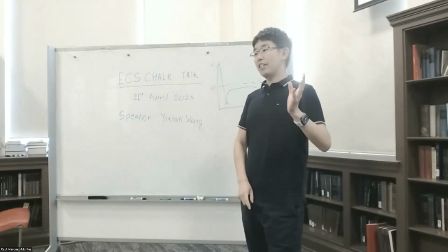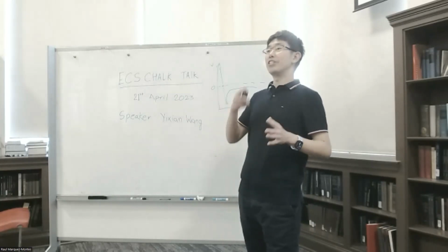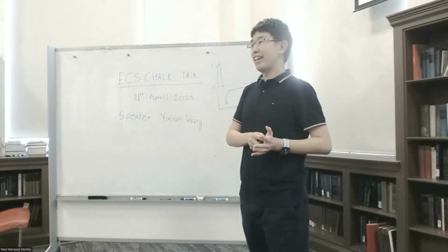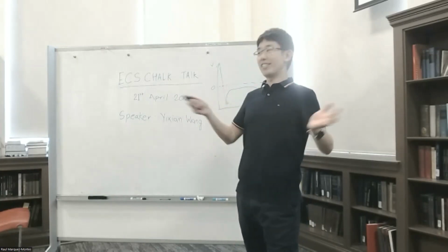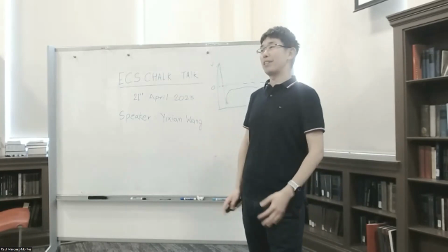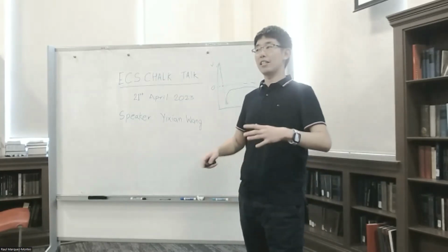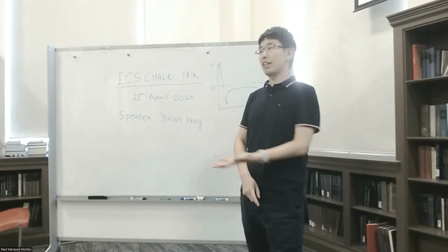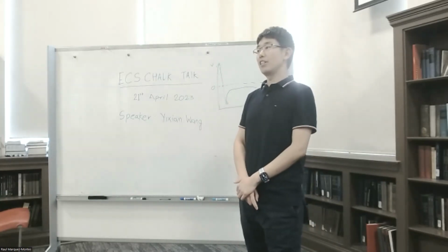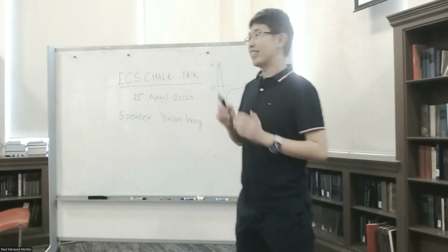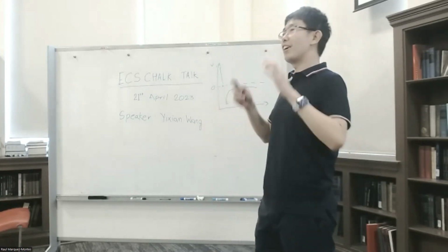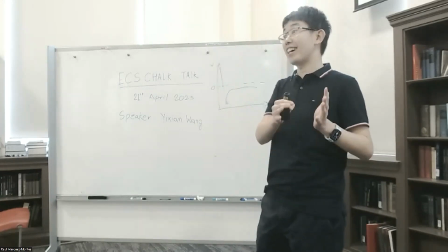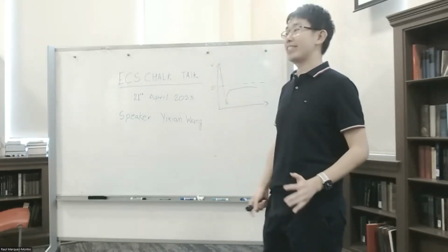With anode-free, people are trying to say, how about reducing the amount of lithium on the lithium metal side, and the maximum would be completely removing the lithium. That's where the concept is getting more and more attention, because again, safety is the key issue. However, anode-free is no longer anode-free after the first cycle, because after the first charge, lithium starts plating on the current collector. Now it becomes a lithium metal battery.